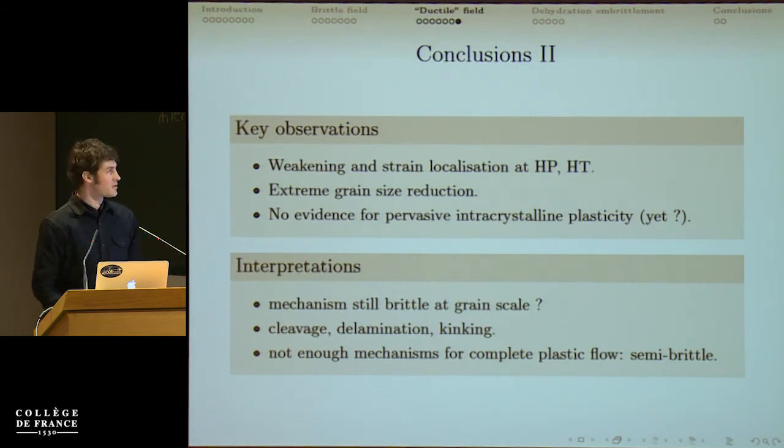So we interpret this as the mechanism being still brittle at the grain scale. So we have cleavage, delamination, and maybe some kinking of the crystals. And of course, we never have enough deformation mechanisms to have complete pervasive plastic flow in this rock, so it remains semi-brittle. We have to fracture the material to accommodate all the deformation.